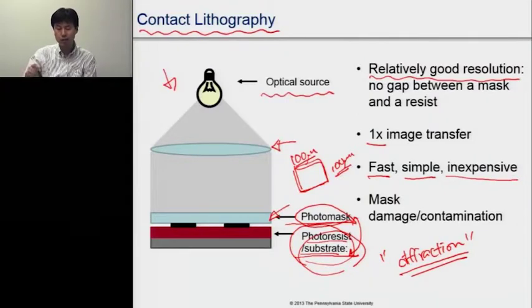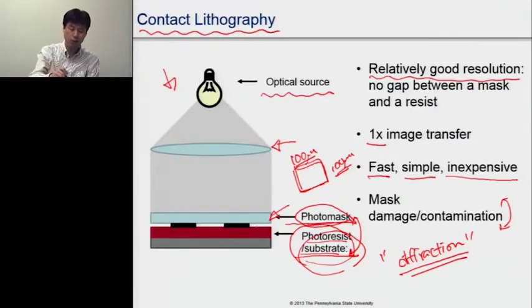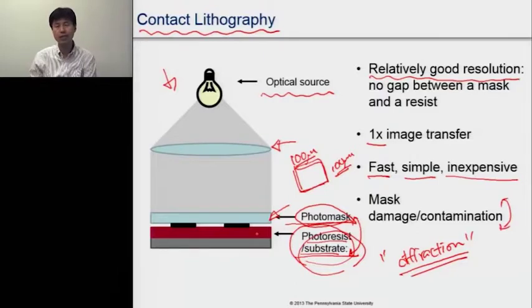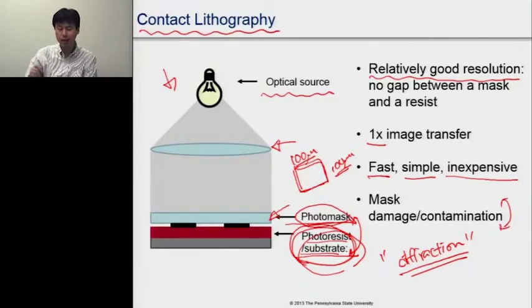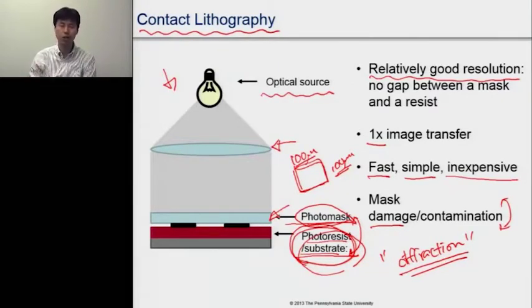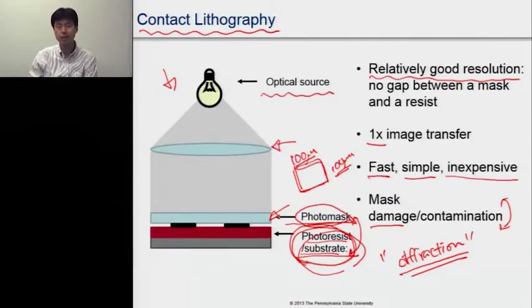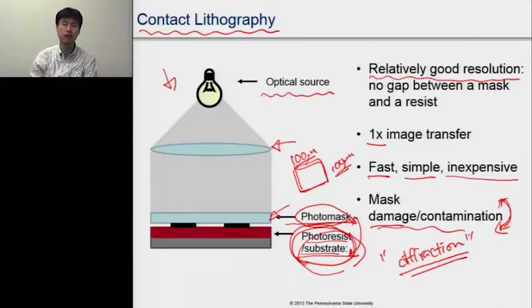However, this technique has weaknesses. Since the photo mask is always touching the photo resist, some photo resist can contaminate the photo mask. Also, if there are particles on the photo resist or substrate, making the photo mask touch the surface can cause physical damage to the photo mask. That is the main weakness of contact lithography.